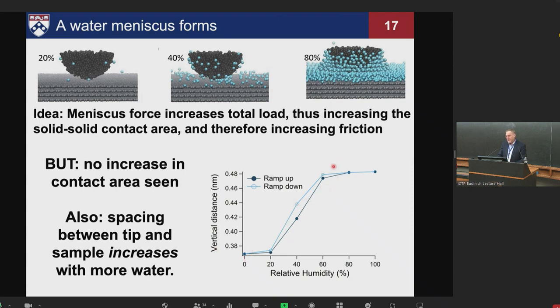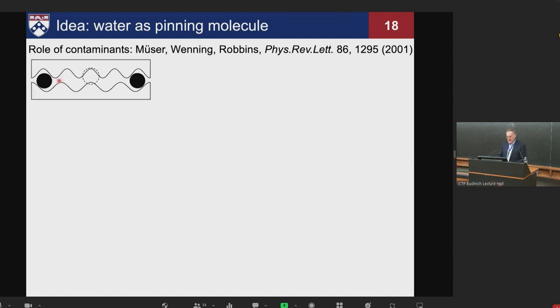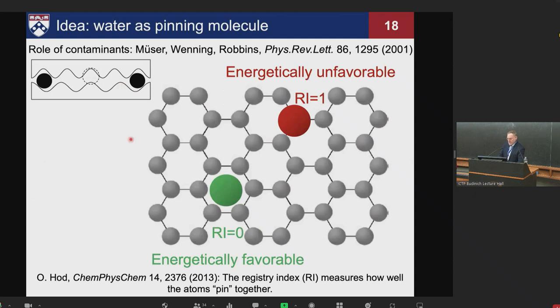But they can resolve it, and outside of the noise of their simulations, there's a clear increase in the height of the tip, not decrease, as the relative humidity goes up. So something else is going on. The contact area model, this adhesion model of why friction changes with relative humidity, doesn't work. The fact that the height increases gave us a hint that there must be water molecules in between the tip and sample, and this is having an effect. And this made us think about Mark's work. You put contaminants at an interface, it can cause friction to go up. So we said, okay, let's take a look at what the registry is between the adsorbed water molecules and the substrate, as well as the tip.